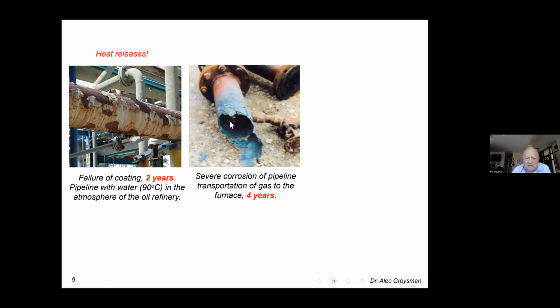The second event, corrosion event, you see severe corrosion of pipeline transportation of gas to the furnace after 4 years of exploitation, use, application. And this corrosion occurs because of hydrogen sulfide releases, and an explosion occurred.